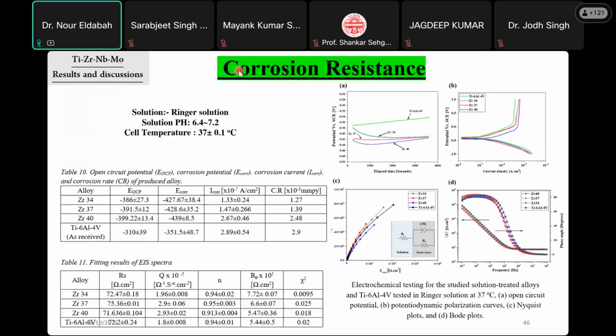For the corrosion resistance, what is important for us is the passivation behavior. So our alloy passivates in this region. A passive layer will be formed in our alloys and a low corrosion rate, and this is very important for long-term duration and dimensional stability of the implant.